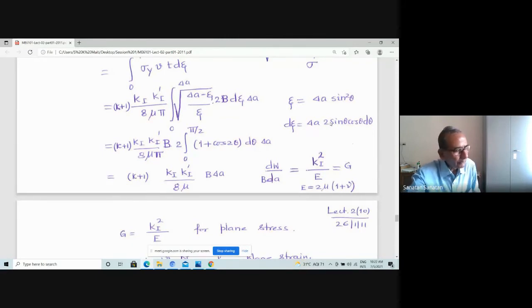I think this is also a very important point. Please understand that the work done in closing the crack per unit area is equal to the energy which gets released as the crack extends from some size to another size. And that energy per unit crack extension is given by K1 square by E. And in fact, that is nothing but the Griffith strain energy release rate G. You see, this is a very important stage of development in fracture mechanics, that Irwin was able to really link the Griffith theory to his concept of stress intensity factor.